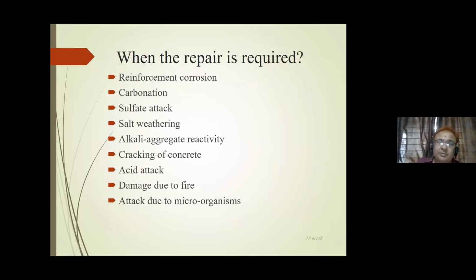Now the repair is required. Repair is required where there is reinforcement corrosion, then carbonation. Carbonation very much affects the exterior column or beam or any structural member. As per thumb rule, 1 mm of carbonation per year should be there in the concrete. If the cover is 20 or 25 mm, within 20 or 25 years it reaches near the steel. So you have to go for a protective coating on the exterior part of the concrete so we can avoid the carbonation.